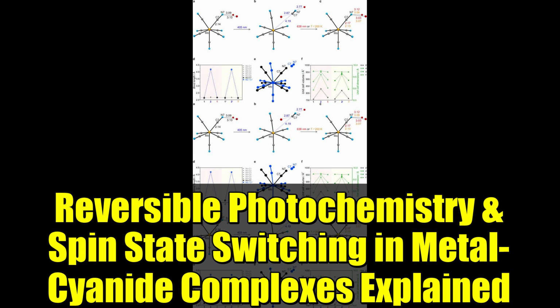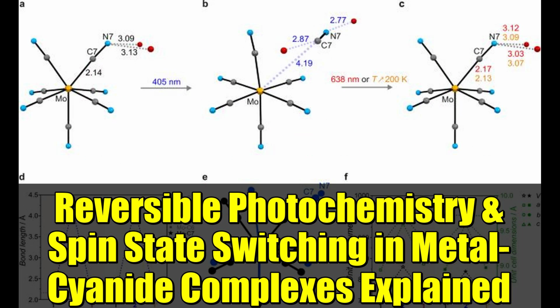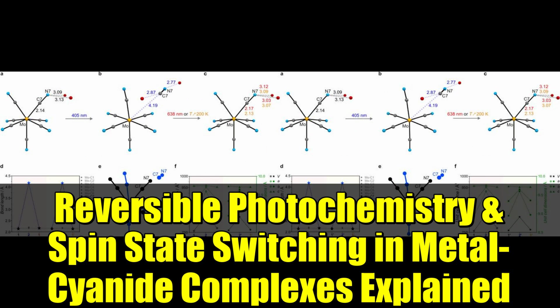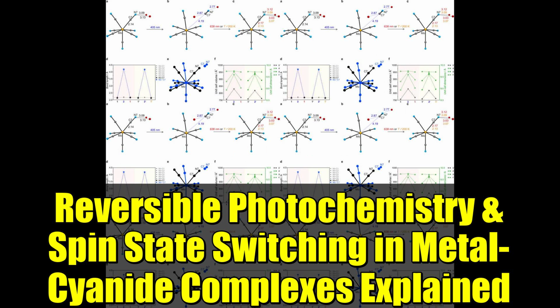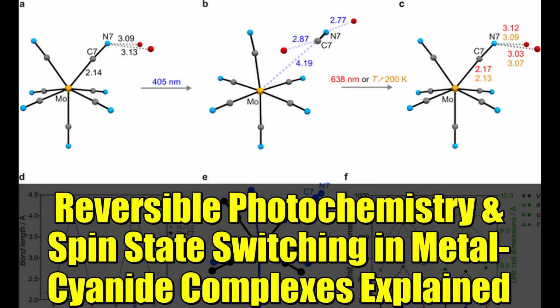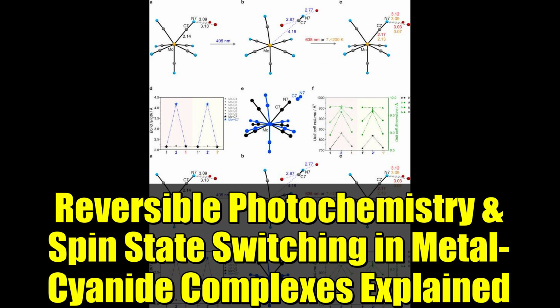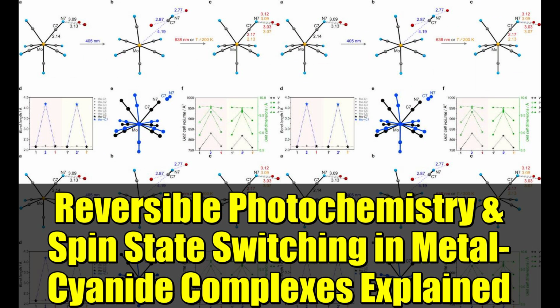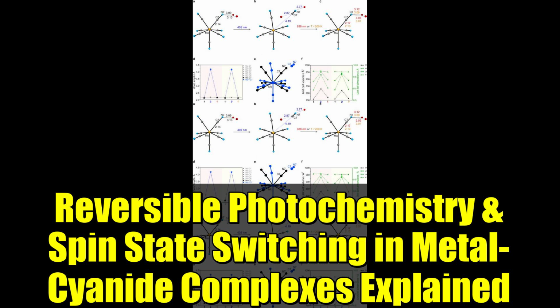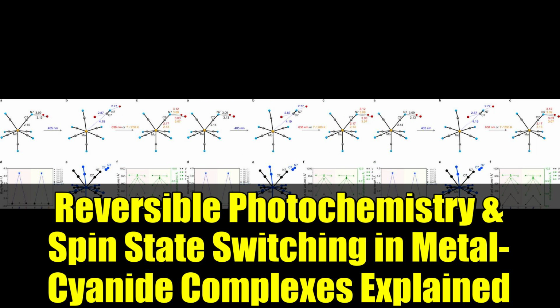The reversible photodissociation of the metal-cyanide bond was confirmed by IR spectroscopy in a polycrystalline sample of 1. XAS measurements at 4 K before and after irradiation supported the photo-induced formation of [Mo(CN)6]3-. The magnetic and in situ photomagnetic studies of 1 were conducted using variable temperature/magnetic field magnetometry with light delivered to the sample chamber through an optical fiber.